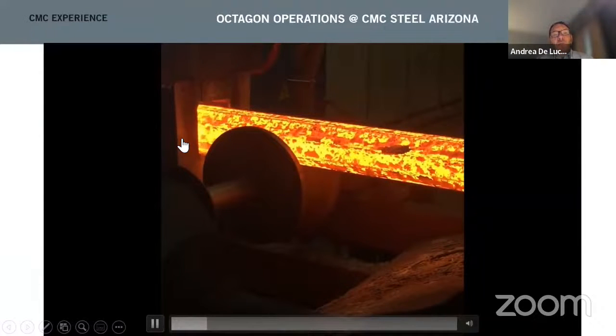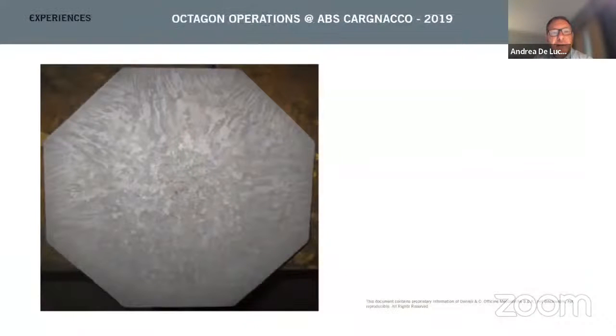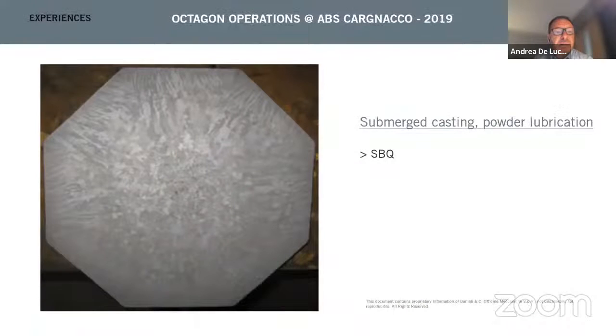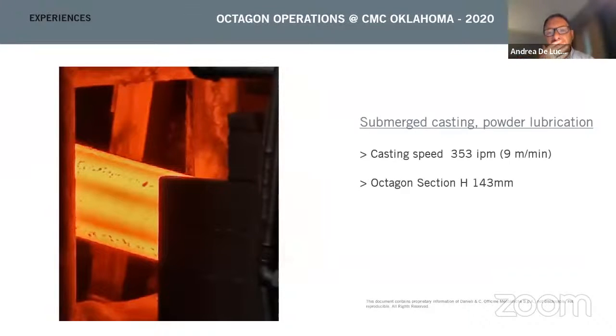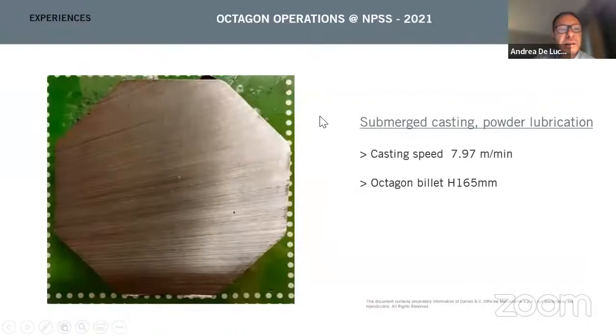Then we applied the octagon, and the quality is the same as the round section, but increasing the productivity by almost 50% of the maximum productivity of the round. But coming back to the rebar and the MIDA application, CMC applied the octagon on the second MIDA plant in the US in 2019, and they are casting up to 350 inch per minute, 9 meters per minute with the octagon. The same in Egypt.